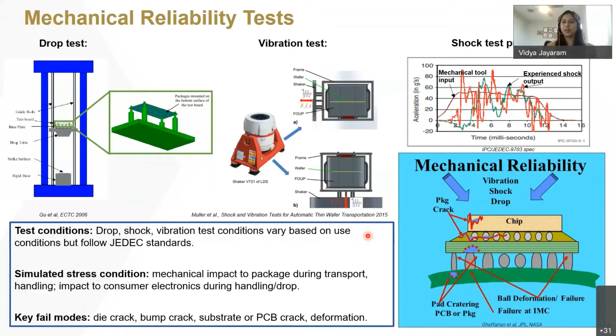What's also interesting here is if you look at the plot on the top right, you see the mechanical input signal that's been provided to the package, but the response, or the experienced shock output, follows a similar curve, but the response is different compared to the input. That tells you that there are so many different materials and process steps involved in assembling your final end product that each of these materials, because of their processing conditions, react differently to shock, and you would see different kinds of failure modes accordingly.